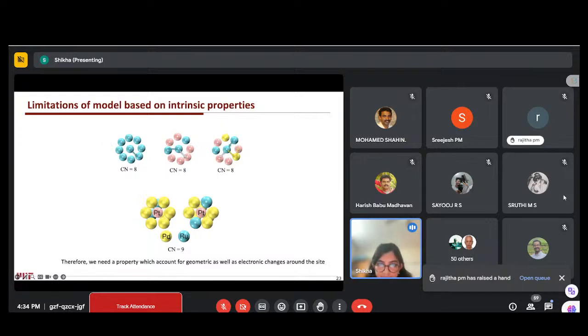So we have three scenarios here. The coordination number of the site is the same in all the cases, but the interaction of the site with the surrounding would be different. So the bond energy, the metal energy in this case, would be very different than the metal energy in this case, because now the property of this metal site would be different than the central site. And if we add more, different atoms around the site, then the catalytic activity for this site would be very different than these two cases. So if we have a fixed coordination number for a given site and we change the surrounding, by changing the surrounding we can change the activity of the site.